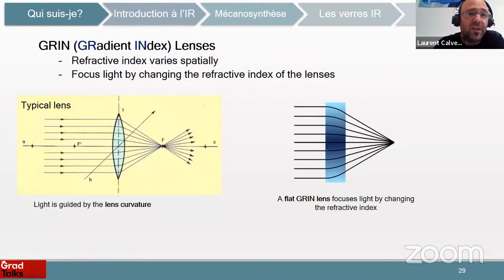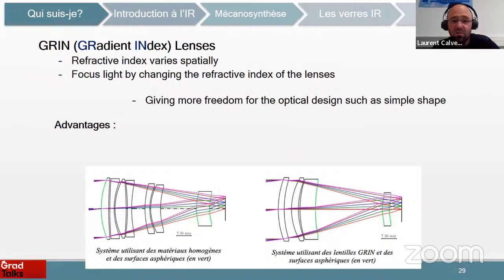So we wanted to use GRIN lenses, which means gradient index lenses. This means that the refractive index will change spatially, and the light will be focused by changing the refractive index of the lens. So here is a classical lens, where the light is deviated because of the curvature. But in our glass, with a flat GRIN lens, which is very flat here, when you change the refractive index from the center to the side, you also get the deviation of the light. It's very interesting for us because it gives more freedom for the optical design and very simple shapes.